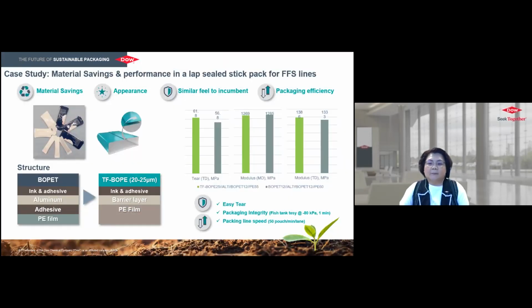Lap Seal Stick Pack, when compared to traditional sachets or thin seal articles, demonstrates a unique proposition in which typically we can save material in the range of 10% to fabricate a small package with the same amount of content. With the use of TF BOPE, recyclable Lap Seal Stick Pack is now a reality. By using TF BOPE as print replacement substrate to replace BOPET for traditional structures, there is no significant difference in terms of tear resistance, as well as stiffness, which affects the feel of the stick pack, as shown on the bar chart on the right. Further evaluation of TF BOPE-based Lap Seal stick packs can still provide the easy tear demanded by end users while maintaining pack reliability and integrity.